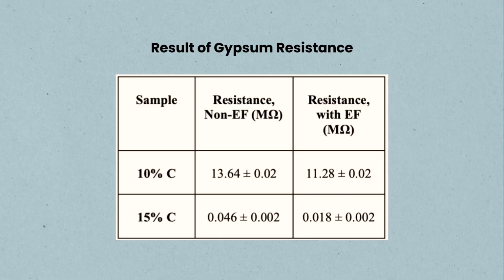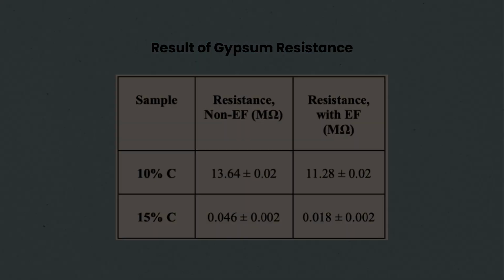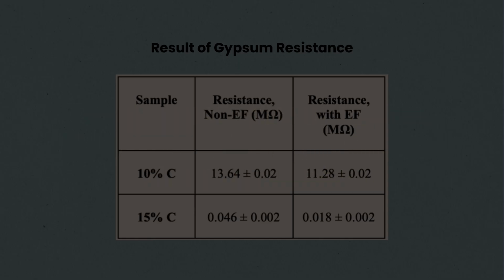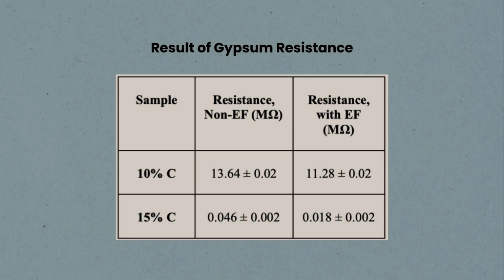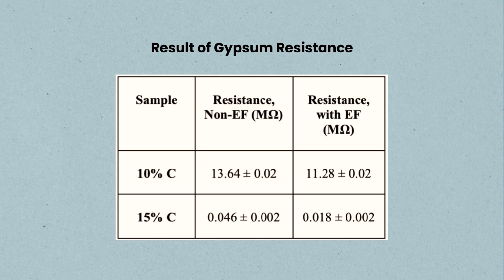In this experiment, only the 10% and 15% carbon gypsum can be measured with a multimeter. The gypsum without carbon, and the 2% and 5% carbon gypsum were all unmeasurable, indicating the conductivity is lower than the measurement limit, which was 0.0031 per mega ohm centimeter. Among all the samples, the electric field gypsum with 15% carbon has the highest conductivity.